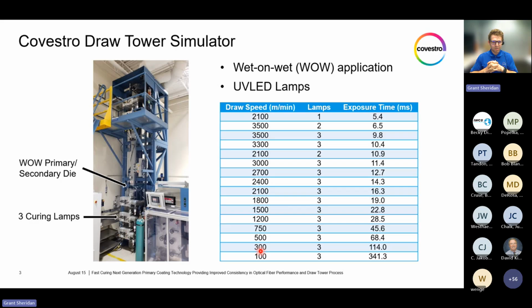This allows us to access an order of magnitude in exposure times, from over 300 milliseconds all the way down to about 5 milliseconds for the shortest exposure time. Being able to vary the exposure time over this wide range really lets us evaluate these coatings and compare the next generation coating compared to our current coating technology in terms of cure speed and mechanical property buildup.